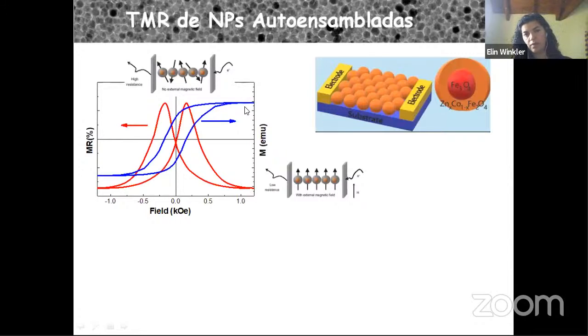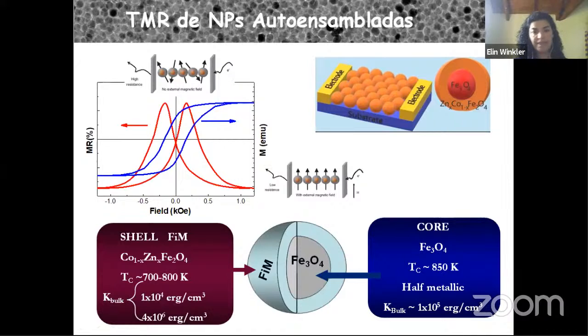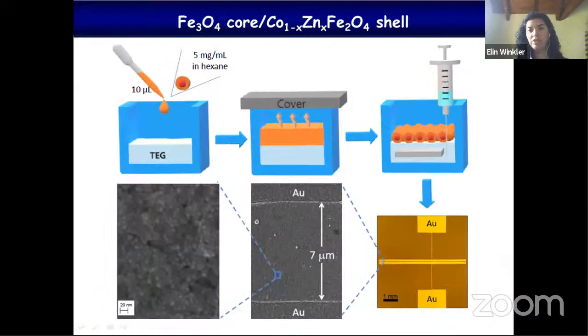Well, the blue line corresponds to a sketch of the coercivity, and the red line corresponds to the magnetic resistance. Again, when all the nanoparticles are oriented, we expect that the tunnel conduction probability will be larger, which means that the resistivity will be lower. And when the system is disordered, the resistance of the system will be larger, or the conductivity will be lower. So we fabricate the system where, again, we keep the core, in this case magnetite, and we change systematically the shell.